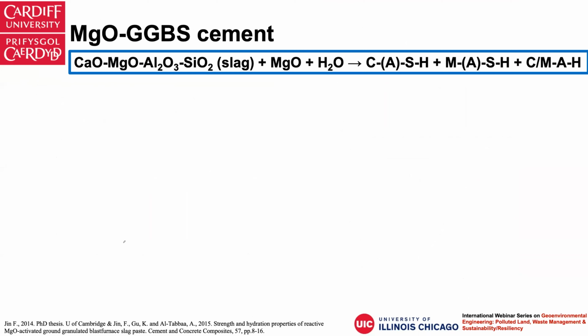And the last one I would like to introduce is Magnesia-bearing alkaline active cement. That is based on magnesia and GGBS. GGBS is a byproduct from the iron making industry. So the composition is quite complex. It is a glassy structure, mainly composed of calcium oxide, magnesium oxide, alumina, and silica. So if you subject it to XRD, it is an amorphous hump. It's a very broad hump. There's no crystal structure of this.